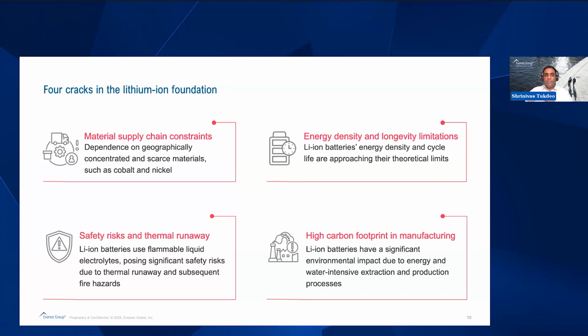The other important challenge is energy density. Lithium-ion batteries are approaching their theoretical limits when it comes to energy density. Practically, they provide around 230 to 240 Wh per kg, and their theoretical limit is around 350 to 400 Wh per kg, and this restricts effectiveness in applications that require high energy density, such as long-range EVs or aviation. There are incremental improvements happening within lithium-ion batteries, like adding silicon to anodes or using high-nickel cathodes, and with this they are improving energy density to a certain extent, but we are not expecting lithium-ion to suddenly double the energy content. And this becomes a major problem for certain applications.